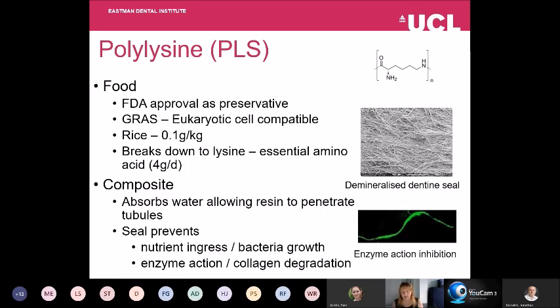But in the body, what it does is it breaks down into the essential amino acid lysine that we need in order to produce more collagen. The daily intake of lysine can be anything up to 4 grams a day. In the composite, what we've found is that the polylysine absorbs water out of the tubule structures, allowing the resin to penetrate in. So what this does is it seals off the tubules, stops nutrient ingress, which would stop the bacterial growth. We also stop the enzyme action, which causes the collagen degradation.